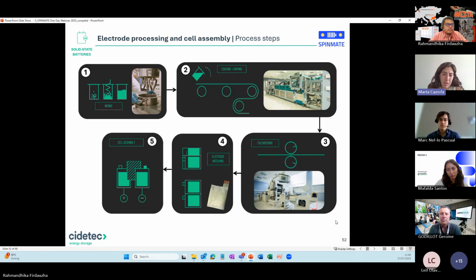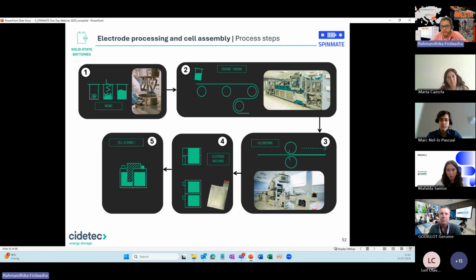Yes, so what we monitor is the thickness, and first the weight and the thickness, and then the pressure of the calender equipment is monitored. Actually, this is what we fix, and then we make the electrode go through the calender, and then we measure thickness, and that iterates until we reach the density and loading values that we want. Sometimes we go over, and then we need to restart. But it's the pressure. It's like a hydraulic calender we use, in some cases.